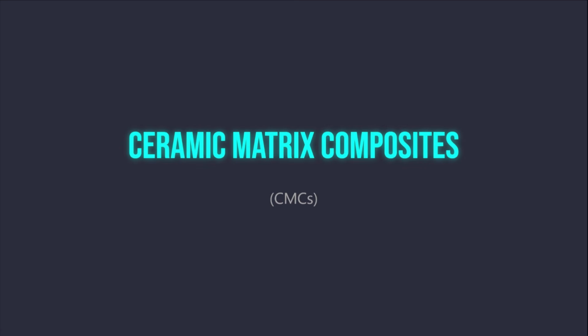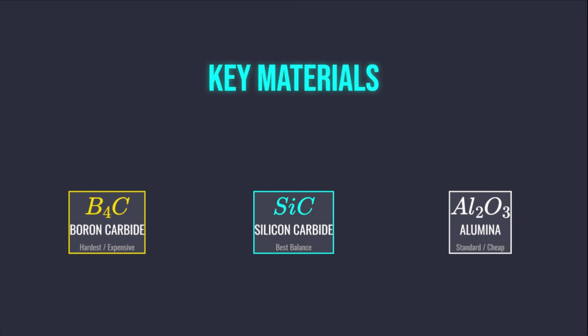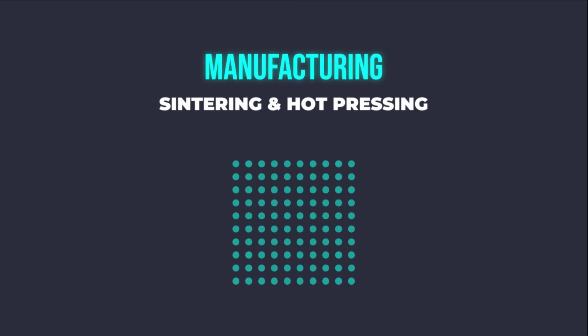Ceramic Matrix Composites, or CMCs, are defined by a ceramic reinforcement embedded within a ceramic matrix, but in armor applications like Chobham, the term often refers to the ceramic metal composite structure. The key ceramic materials used include boron carbide, silicon carbide, and alumina. Boron carbide, with a Mohs hardness of 9.3, offers exceptional performance against tungsten carbide and depleted uranium penetrators, but is significantly more expensive and challenging to manufacture into large tiles.